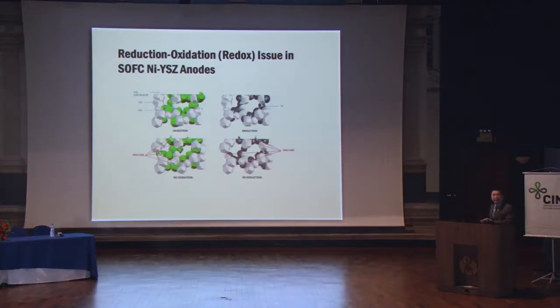So the anode can become unstable because of the volume change during the oxidation-reduction cycle, and that can cause cracking within the anode structure, and so cracking in the electrolyte. So that is the major issue in the SOFC, especially with the cell design based on the anode support structure. So one approach to address these issues is to engineer the microstructure of the anode.